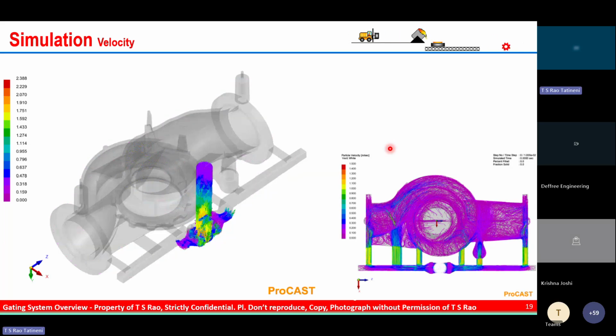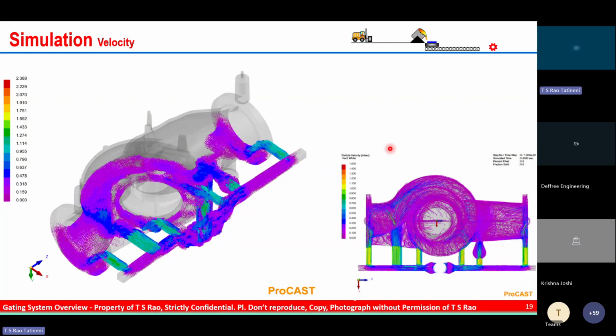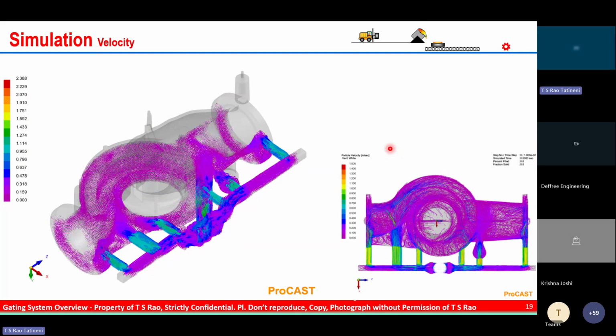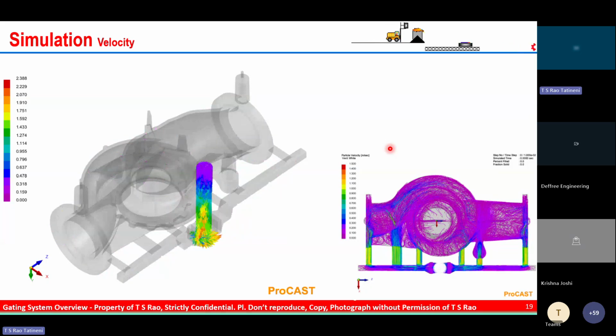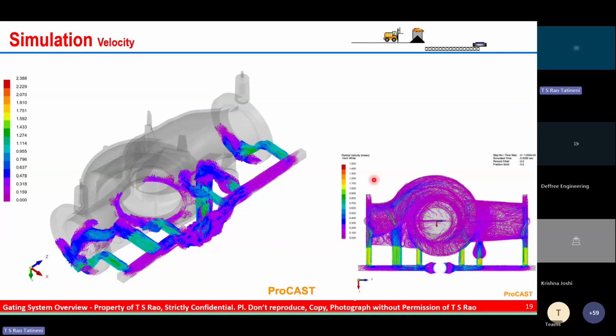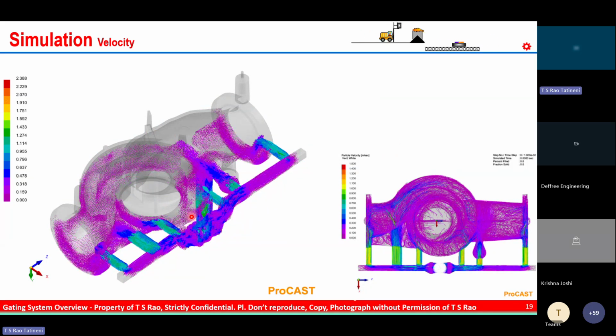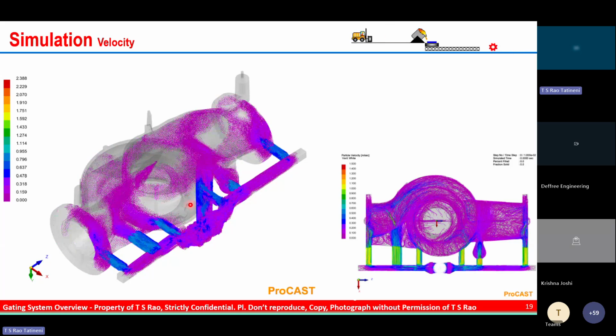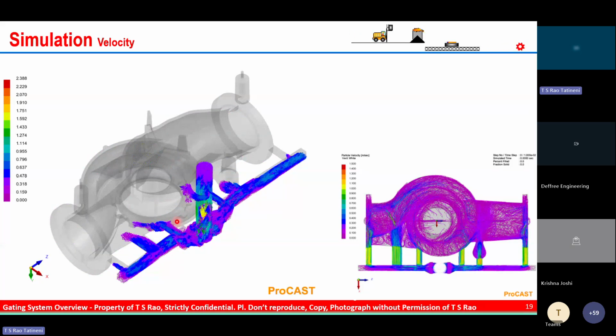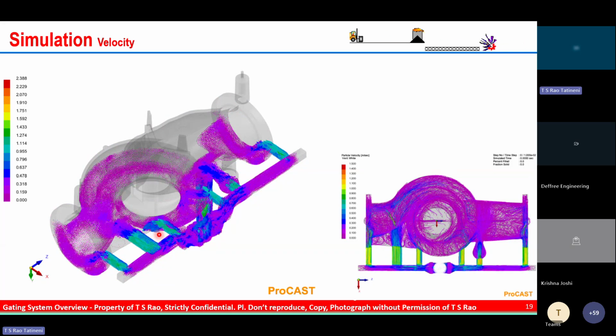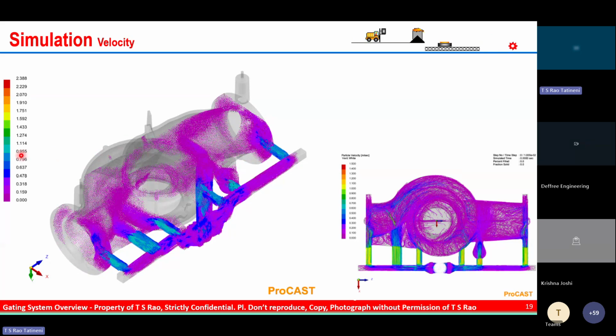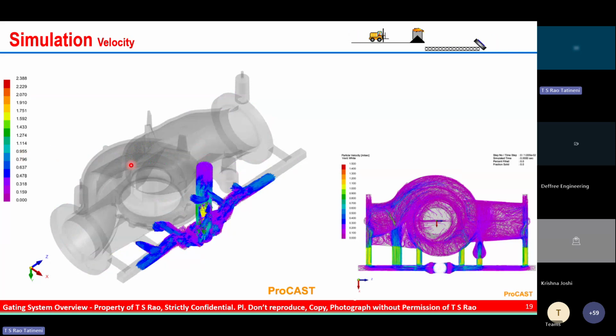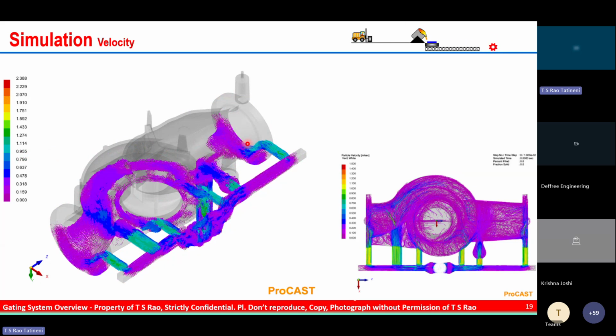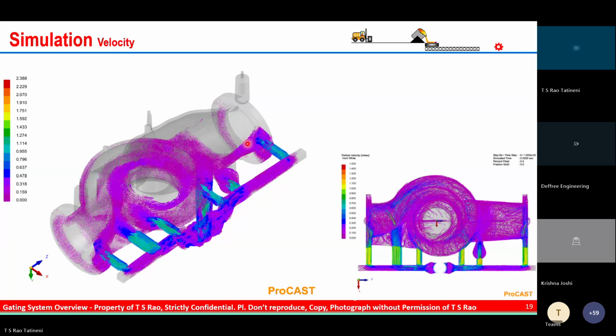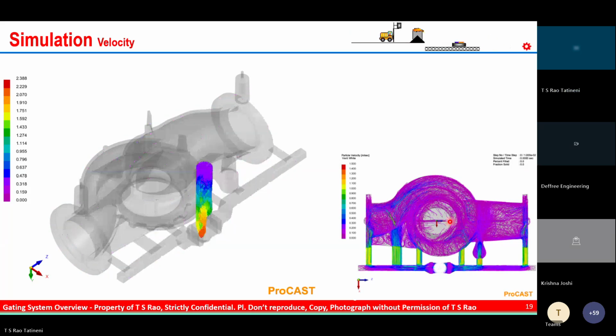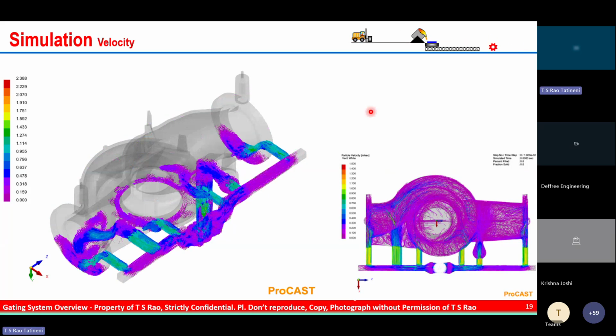Okay. So the velocity is very important with respect to preventing sand inclusions or any inclusions within the casting environment. Anytime the velocity goes beyond 1, there could be some inclusions within the mold environment. You can see in this case, everything is within 1. So this particular casting will be free from any inclusions. Here you can see the velocity mapping.